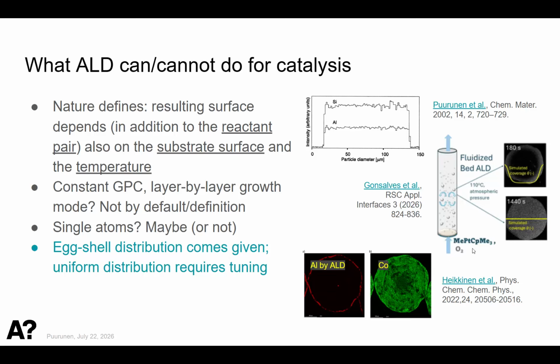This is a collaboration with TU Delft, where we made platinum ALD on alumina spheres that were of different sizes. I think these might be for 1 millimeter size, although I don't remember for sure. And clearly we had first an eggshell coating, but when we elongated the exposure times to over 1,000 seconds, then we had the coating throughout. And we have also simulated these through diffusion reaction simulations, and those also show the eggshell coating that then goes through when we have enough exposure. Exposure meaning partial pressure times time.